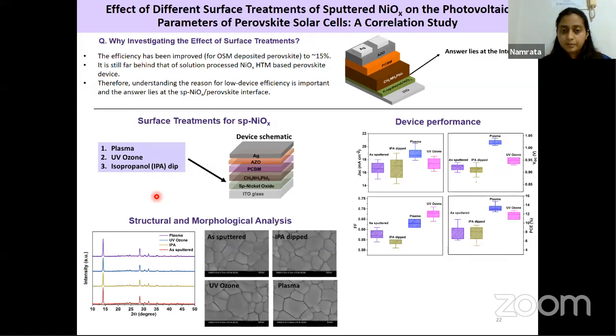And from different literature, it has been reported that these treatments can influence the surface charges of the metal oxide layers. So when we treated the nickel oxide with these conditions and prepared a perovskite layer, we saw that there is no such change in the perovskite crystallinity or the morphology. As we can see from the XRD, the peaks are almost similar, no additional peaks and no change in the peak intensities. Even if we look at the SEM images, we observe that we have almost similar size of grains, and they are all uniform.